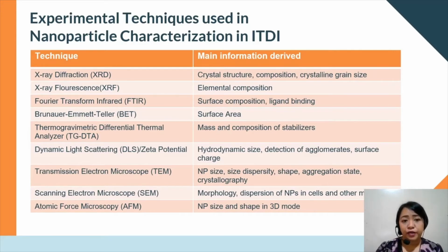For the transmission electron microscope or TEM, we can identify nanoparticle size, size dispersity, shape, aggregation, and we can also identify the crystallography of the material, whether it's amorphous or crystalline, and what type of crystallography it has. For the scanning electron microscope, we can identify morphology, the dispersion of nanoparticles in cells, and other properties. And for the atomic force microscope, we can identify nanoparticle size and shape in three-dimensional mode.